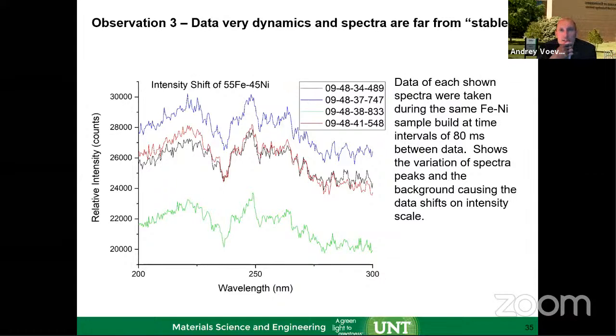And then another observation is that the data itself is very dynamic. This is an example of sintering an iron and nickel mixed composition powder. The peaks present here belong to iron and nickel, but what I'll bring to your attention is these lines in here, how they offset in relative intensity. Also, during the same experiment, with the same powder composition, we take data within 80 millisecond intervals, very short intervals, and you can see here the spectrum has shifted dramatically on this scale. So it creates an additional challenge in how you can compare over time if your intensity is varying. You need to have some common background extraction method for the comparison.